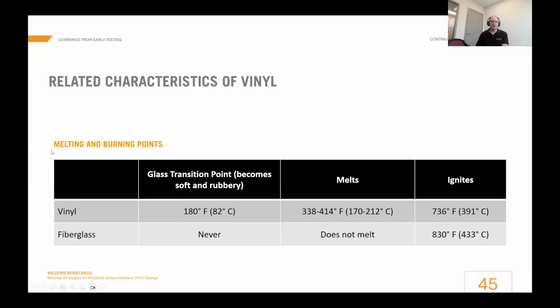When you think about the material characteristics of those two samples, with vinyl there is a glass transition point. The material hasn't melted yet, but that is the point where it becomes soft and rubbery. It's about 180 degrees Fahrenheit when that happens. Fire breach can occur in this situation because it becomes soft and rubbery and doesn't support load the same way it does at normal surface temperatures. It melts at a much higher temperature and it ignites even beyond that. So 736 degrees Fahrenheit was a sort of average that a Google search returned to me.